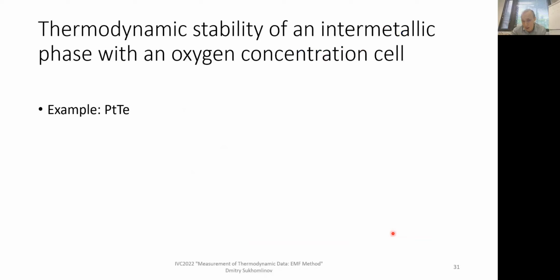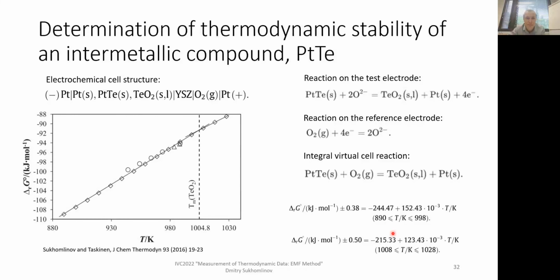Intermetallic system example. We're going to discuss how to measure the Gibbs energy of formation of a substance such as platinum telluride. We are still using an oxygen concentration cell with oxide solid electrolyte, but somewhat indirectly determining delta G of formation of this intermetallic substance. How is it done?